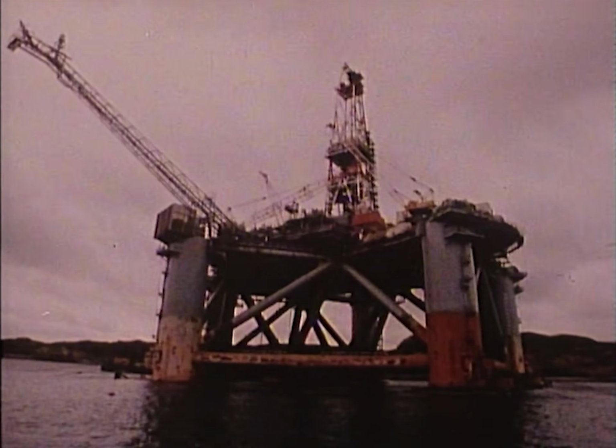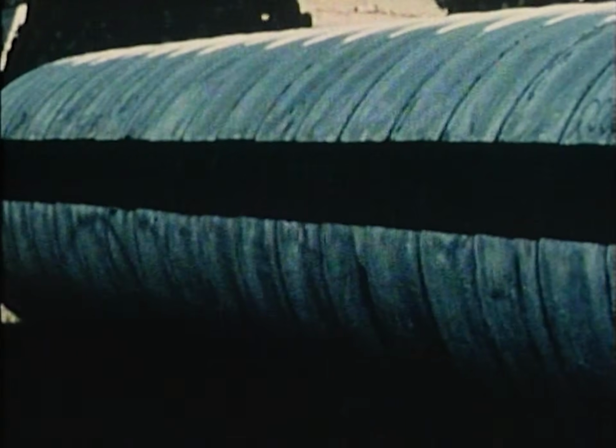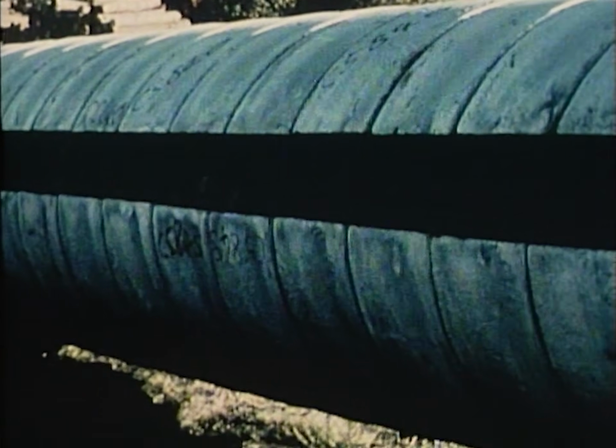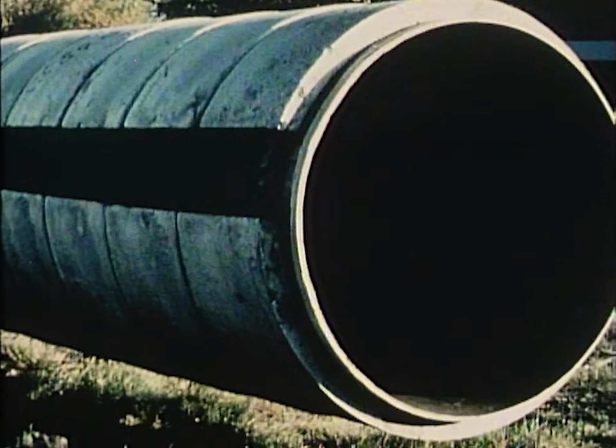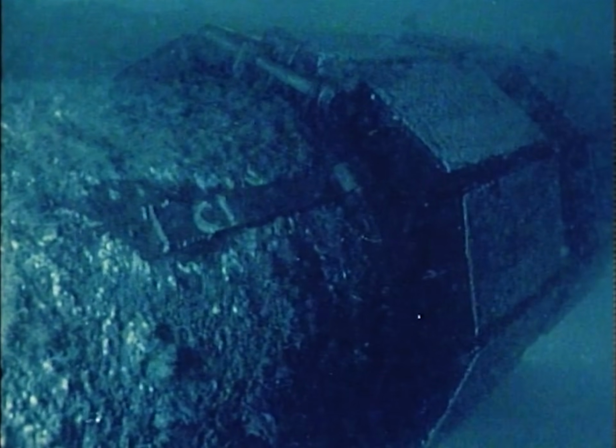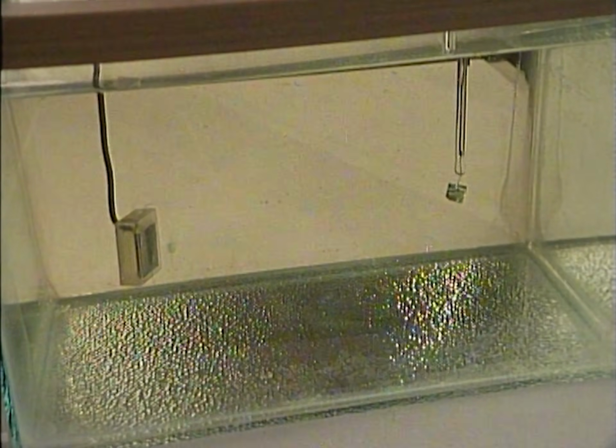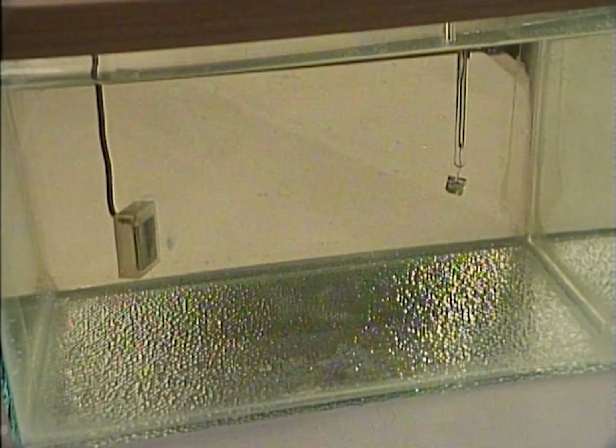The anodes that Brian Wyatt is talking about are what stop these oil rigs dissolving. In practice, they're huge aluminium ingots, up to half a ton in weight, strapped on to the vulnerable legs of the rigs and providing what's called cathodic protection. The natural phenomenon that makes them work is a particular interest to another UMIST scientist, Dr. Vic Ashworth. Well, quite simply, when corrosion occurs, there are two essential things that go on. First of all, the metal dissolves, clearly, and that's what we understand as corrosion. But to a corrosion scientist, he's aware that there's also a current flowing in the metal from the point of corrosion into the bulk of the metal. So there's always this tiny corrosion current flowing. If you haven't got the current, you haven't got corrosion. And if you have got the current, then you have got corrosion. And what we're trying to do in cathodic protection is to back off that current so that you have no current, therefore you have no corrosion.